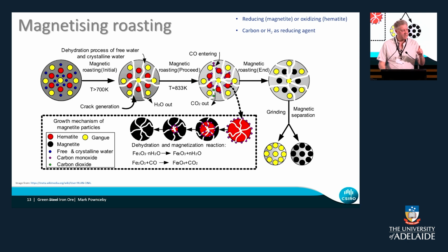The real challenge, though, of course, is when you've got things like alumina and phosphorus and silicon in your goethite, right? It doesn't go to a discrete phase. When you dehydroxylate the goethite, it might rim pores, it might go to very small fine particles that you're just not going to get through straight magnetic separation.